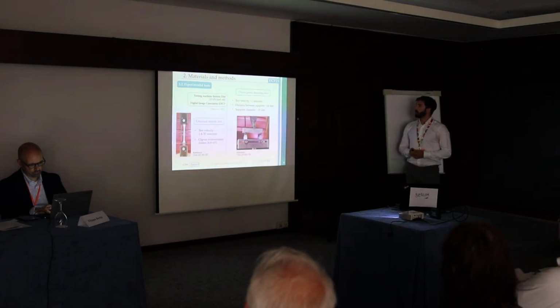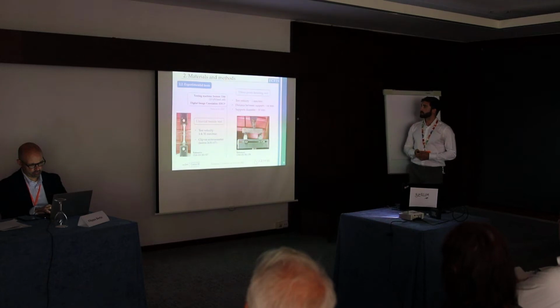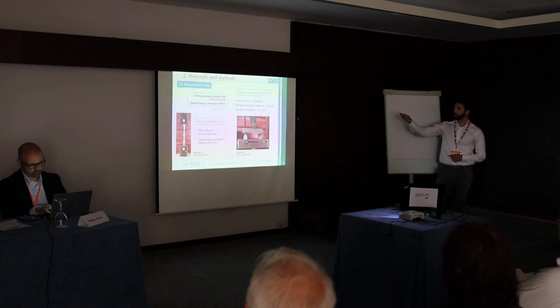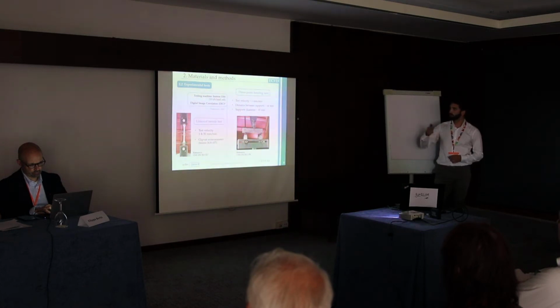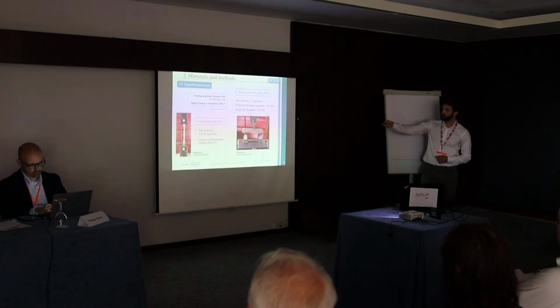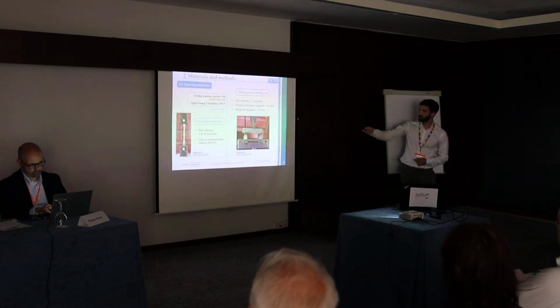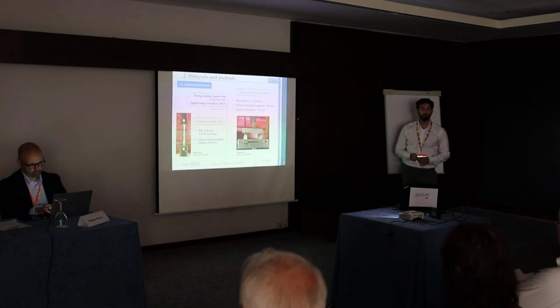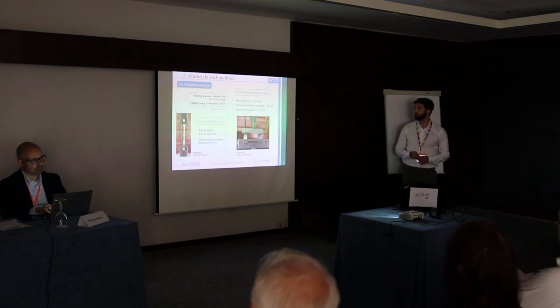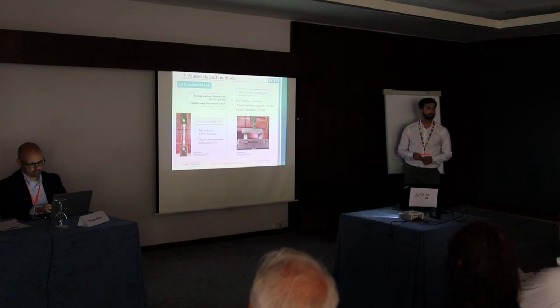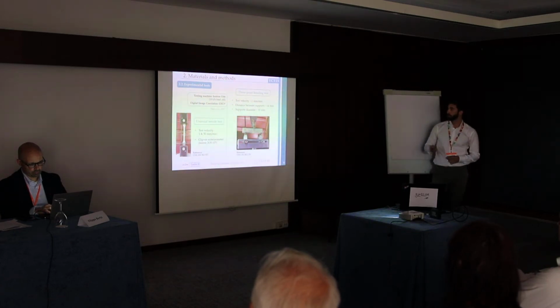Okay. Regarding the experimental tests, for both tests we use the testing machine you see there with a load cell of 10 kN and the implementation of digital image correlation. For the uniaxial tensile test, you have there the setup. We used an extensometer to obtain the strain more accurately, and we made it at two different test velocities, 1 and 15 millimeters per minute, to study the strain rate.